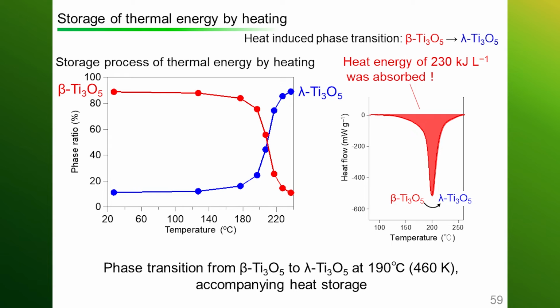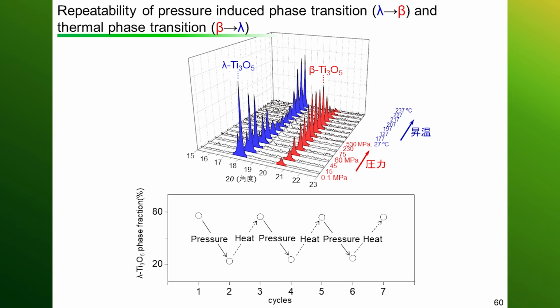In addition, by applying pressure, we obtained beta Ti3O5. We raised the temperature, and at 190 degrees, it returned to lambda again, and was absorbing the same amount of heat energy. At 190 degrees from beta to lambda, the material stored great heat as it underwent phase transition. To repeat, this is the horizontal axis, XRD, but please just look at the peaks. The lambda decreases, pressure is applied, and the beta increases.